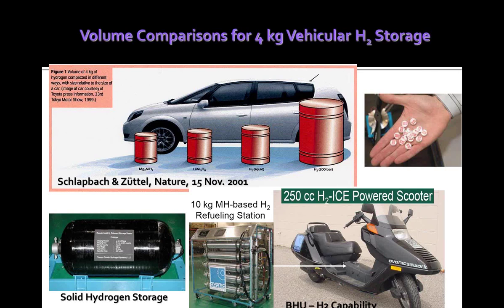So what we did in our research was use metal hydrides made of periodic table elements like lanthanum nickel aluminum or lanthanum nickel mischmetal. Lanthanum is a rare earth material, nickel is a transition metal, and then aluminum, and we make a compound, or magnesium nickel aluminum, magnesium nickel iron, etc. These compounds have the power of absorbing hydrogen at operating conditions, which could be room temperature, a mild temperature, or a little high, like magnesium hydride, which takes about 320 degrees Celsius.